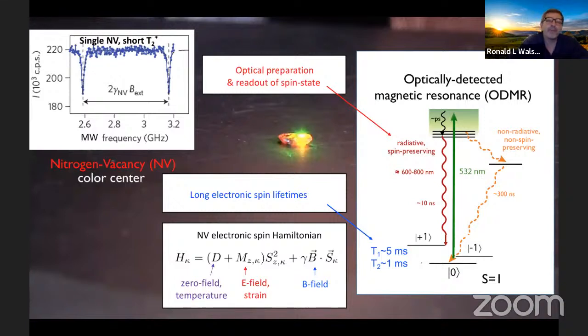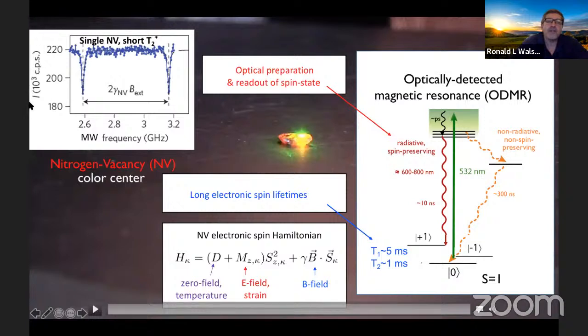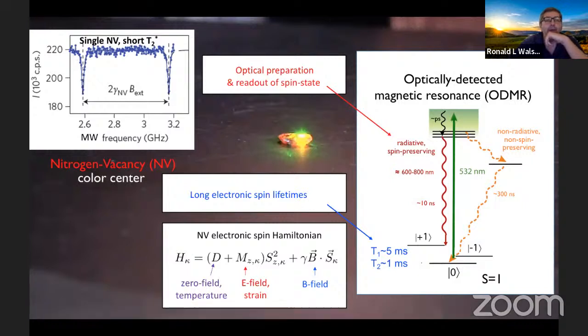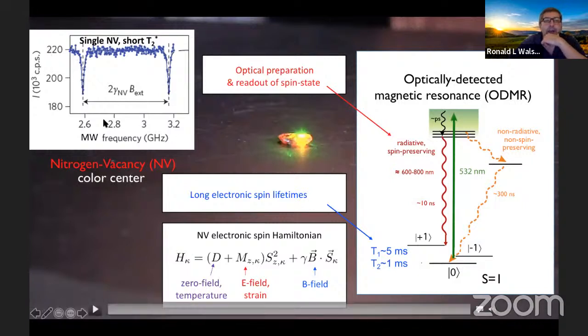easier to understand. So on the y-axis is the intensity of red photons that are being emitted and collected in this experiment, hundreds of thousands per second. And on the x-axis is the frequency of a microwave signal that you're applying to the NV. And it's in the presence of an external magnetic field that's about 100 Gauss. So that 100 Gauss field, like shown in the diagram on the right, will split the 0 to 1 and 0 to -1 transitions by a certain amount. And you illuminate the NV with a green laser, and you're measuring the red fluorescence.